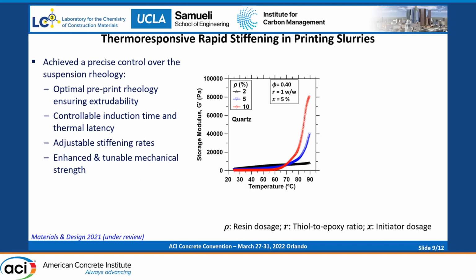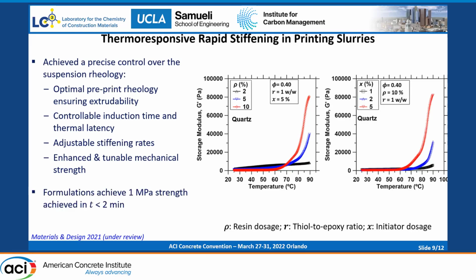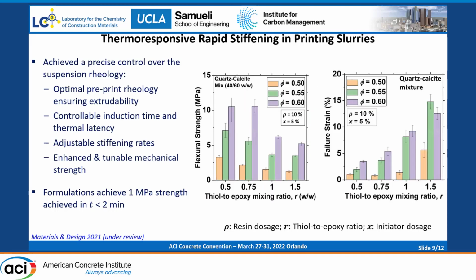This shows the effect of resin as a function of weight percentage of the total solids in the suspensions. We can vary this resin content and induce the kind of thermoresponsiveness that we want. This shows the effect of initiator dosage, where we can bring down the activation temperature. What is shown here is the effect of solid volume fraction and the epoxy-thiol mixing ratio.